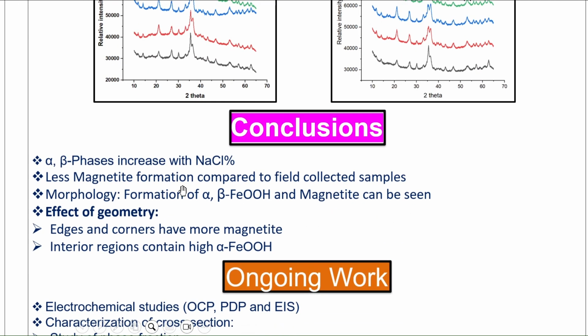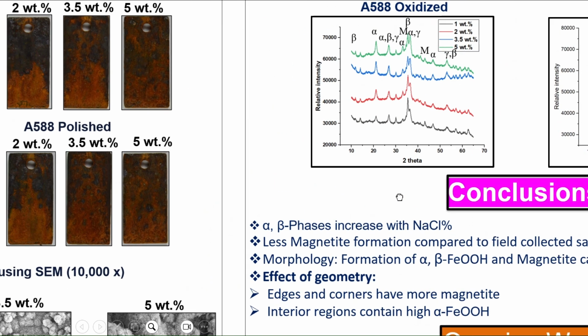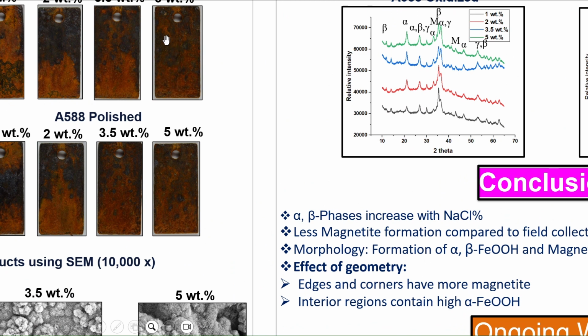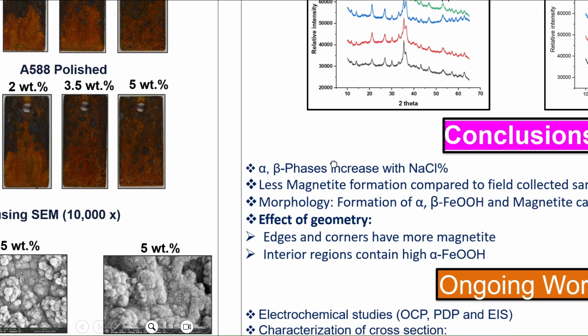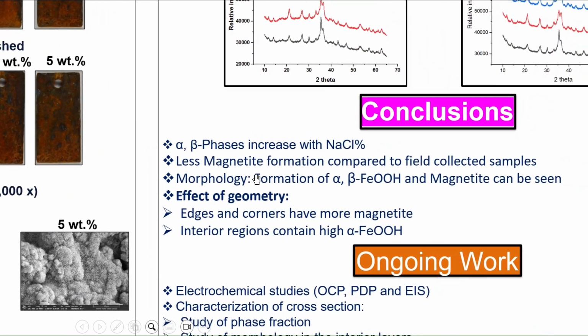and there is less magnetite formation compared to the field collected samples. The field collected samples overall occupy the blackish regions. That's why we can say that they are all full of magnetite. But here in the 400 cycle samples, magnetite formation is very little.